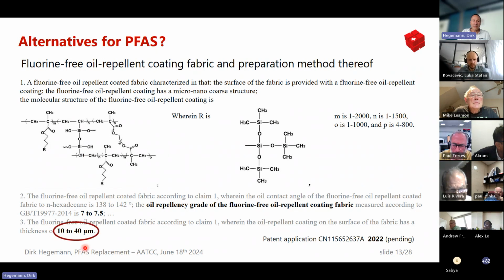However, now you might need 10 to 40 micrometers, so no longer 1 micrometer as with C8, or even less if you do it properly. Now you're in the range of tens of micrometers you need to apply on a textile. You know it's changing the fabric feel, maybe even pressability and other properties.